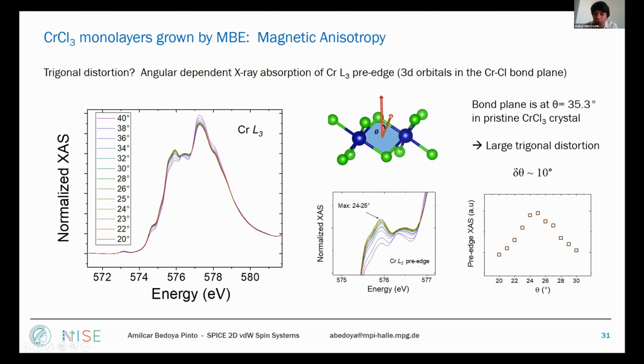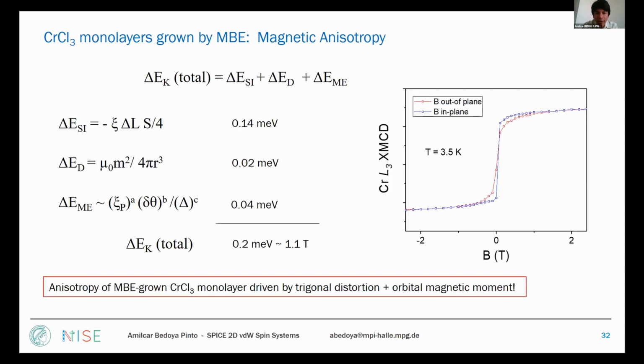And this large trigonal distortion, we believe, could be... we have to do a bit more studies on what this trigonal distortion would represent in terms of strain or real atomic bond lengths. But it's indeed one factor that underlines the high values we have in the anisotropy of this chromium trichloride. So the main message here is that we believe this anisotropy is coming from this trigonal distortion in our MBE-grown samples, which also leads to this orbital magnetic moment anisotropy.